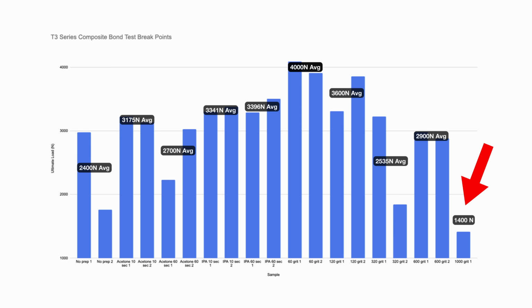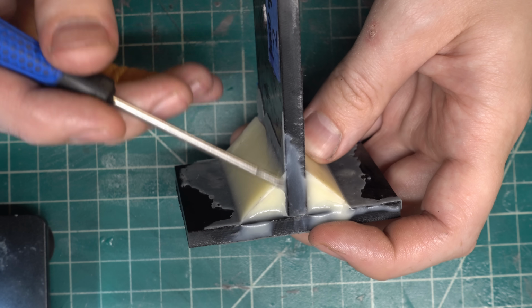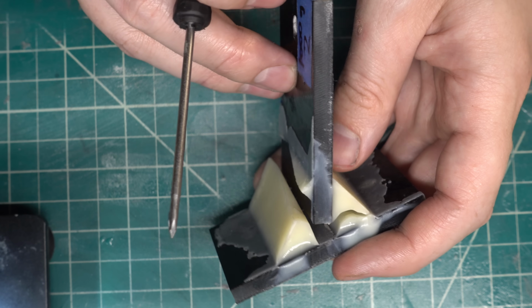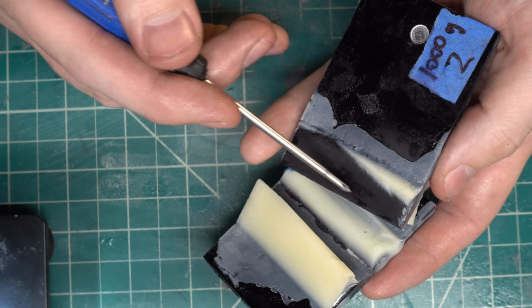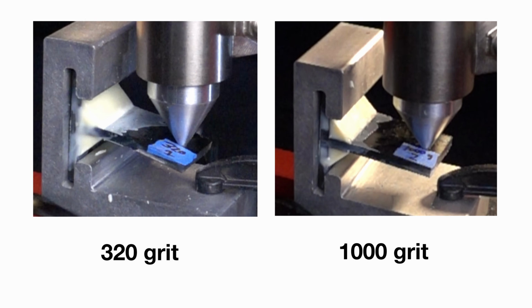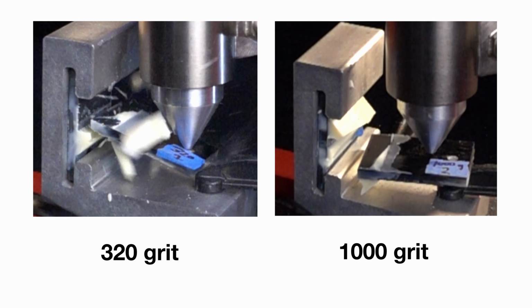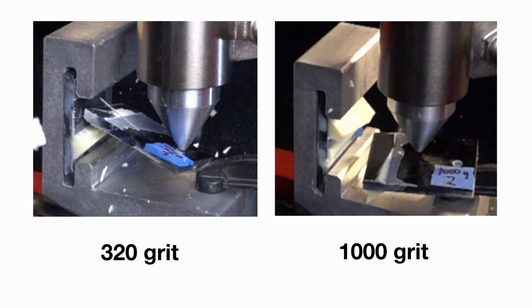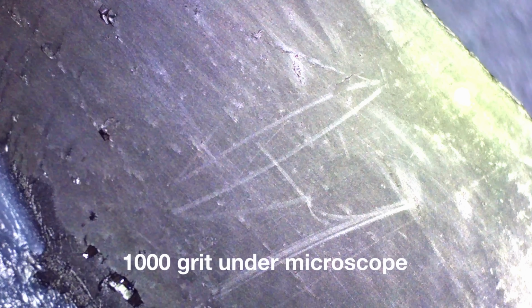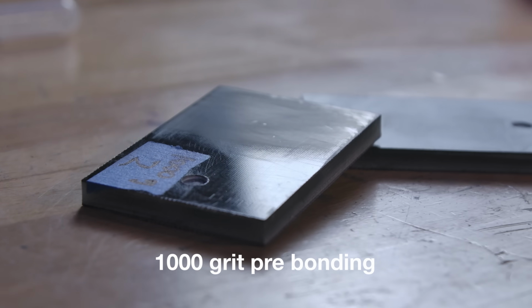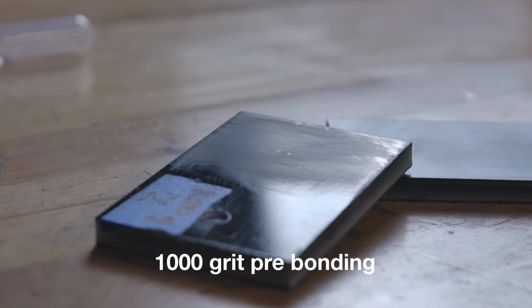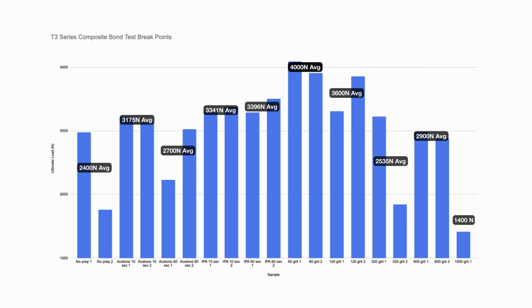For my worst performing sample, the 1000 grit, it looks like we had a real fast delamination on the bending piece of fiberglass, and this is consistent with the high-speed footage. The coupon just lets go with very little violence like we see in other break tests. The top layer of resin almost looks untouched. It almost seems like we had some contamination on the surface, which is strange because I wiped it down with isopropyl alcohol after sanding. But let's take what we can learn from the 60 grit and see if we can get higher than that 4,000 newton number.